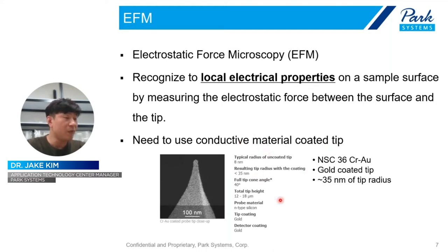like this. Conductive material means, for example, gold or platinum or conductive diamond and some other metals. And it is one good example of a conductive material coated tip. This one is a gold coated tip. And one interesting thing is that a normal AFM tip has around 10 nanometer tip radius. But in the case of this conductive material coated tip, because of this coating, the tip radius becomes a bit larger, for example in here 30 or 40 nanometer, but sometimes more than 100 nanometer. So we need to remember this radius is different.